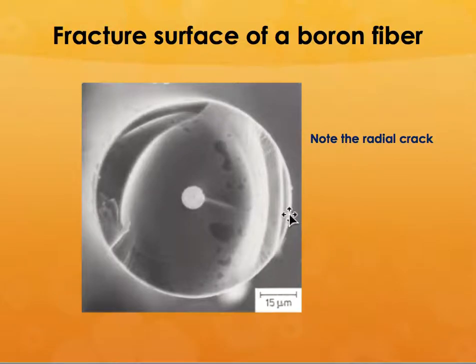So this shows you the fracture surface of a boron fiber. You can see that it is pretty brittle and it shows radial cracks. This is a radial crack starting from the tungsten fiber, and tungsten fibers are not as ductile or flexible like boron, so the fracture will tend to start from that point and radiate out.